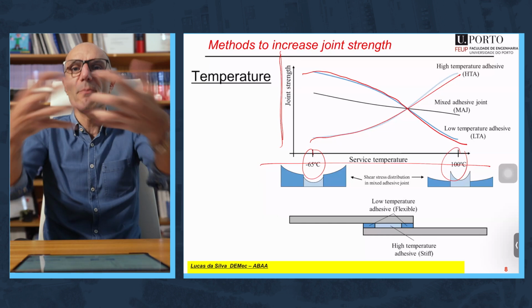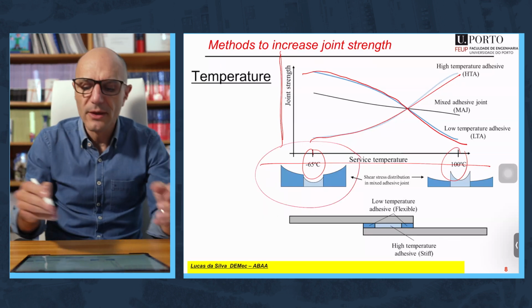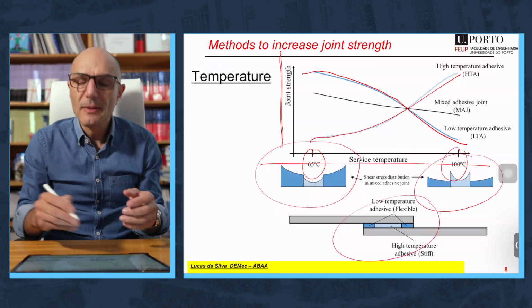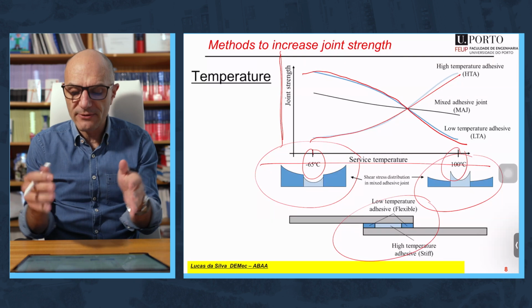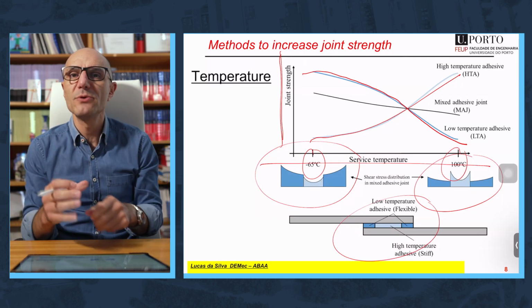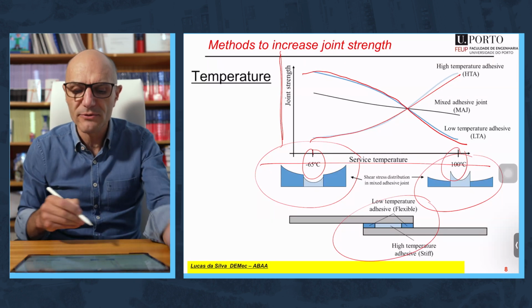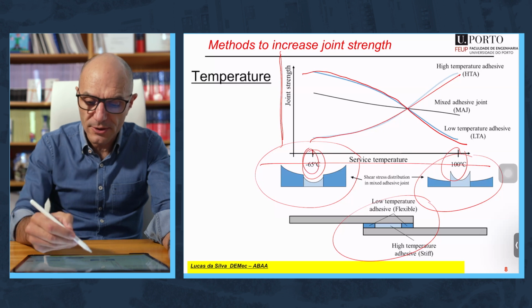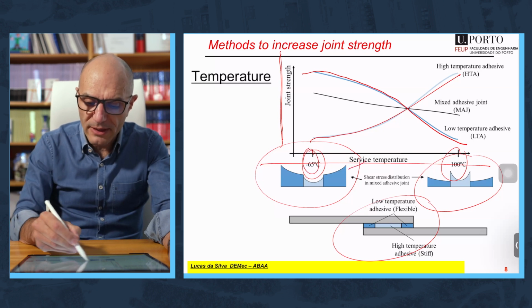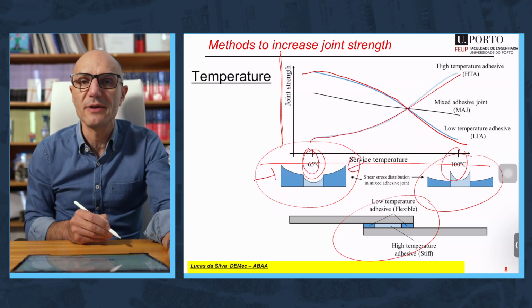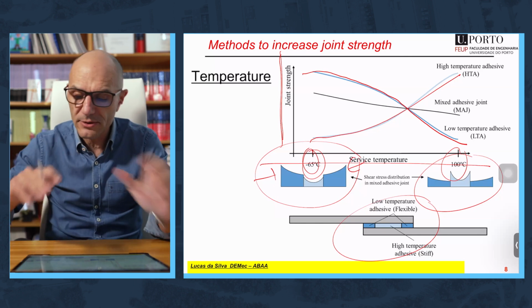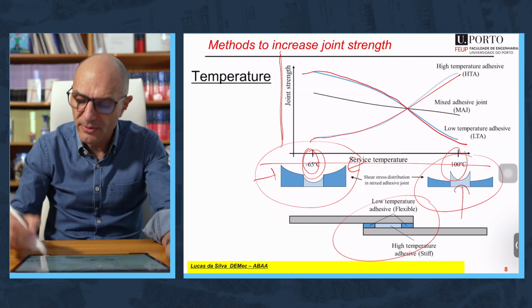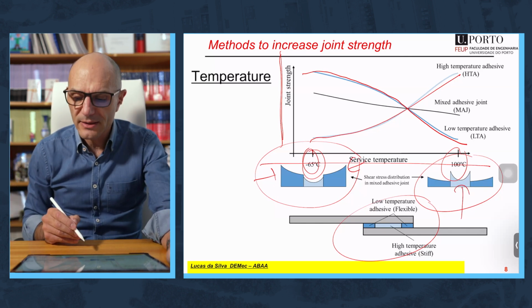But what you can do is combine the two, as indicated here, or here. You put the low temperature adhesive at the ends of the overlap, and you put the high temperature adhesive in the middle of the overlap. When you are at low temperature, it's the low temperature adhesive that is at the ends of the overlap that works. When you are at high temperature, it's the opposite. It's the high temperature adhesive in the middle of the overlap that works.